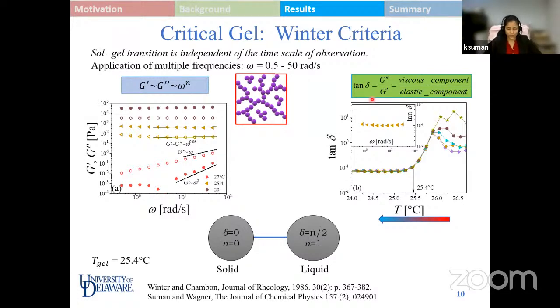Now, since at the point of critical gel transition both the moduli obey identical power law dependence, the ratio of the two, which is tan delta, mathematically should become independent of the applied frequency. On the right curve over here, the different colors of the curves correspond to different frequencies. As we can see, at 25.4 degrees all the tan delta curves intersect at a point and become independent of the applied frequency. Therefore, with this experiment, we are able to carefully characterize the critical gel temperature of the system, which is 25.4 degrees centigrade.